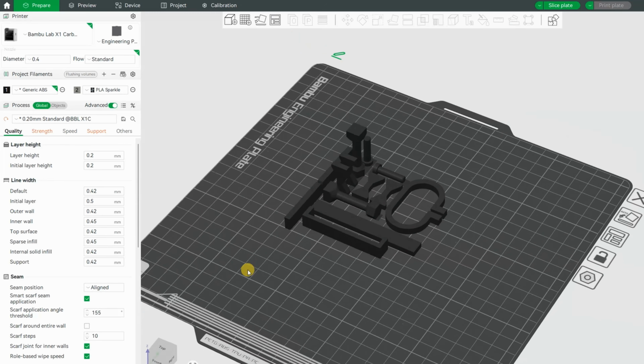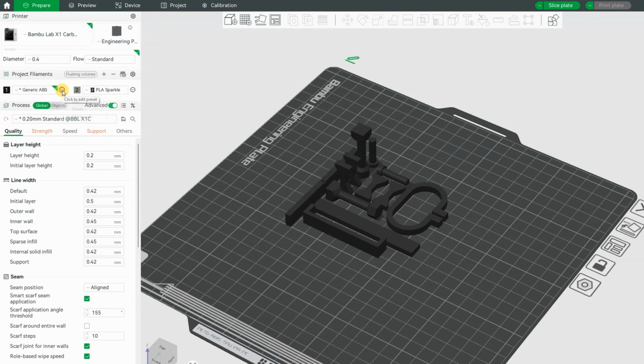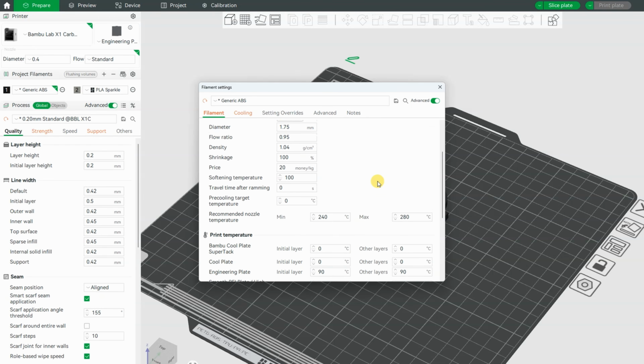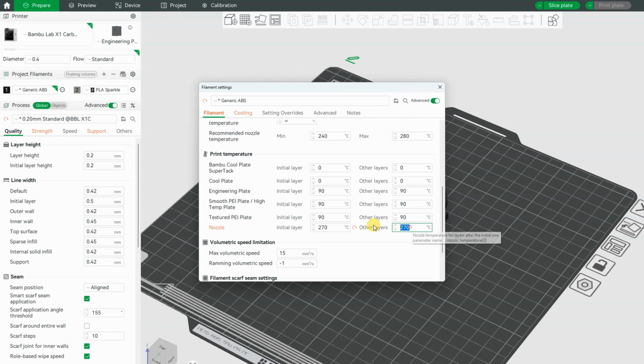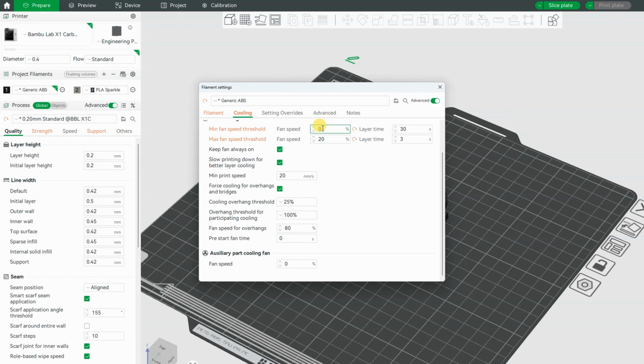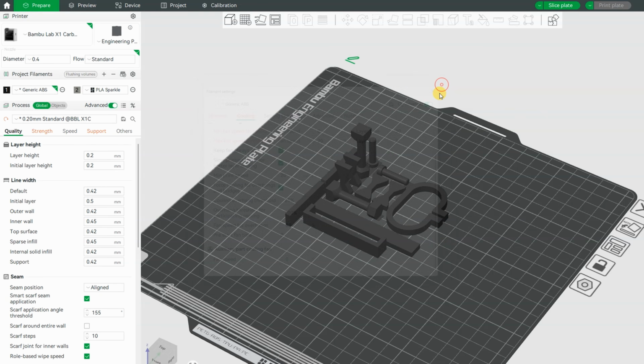Settings in the slicer: I'm starting from the generic ABS profile. The nozzle temperature is 270 degrees Celsius, 15 is the maximum flow, and I reduced the part cooling to only 20%. Later I will test different percentages too.